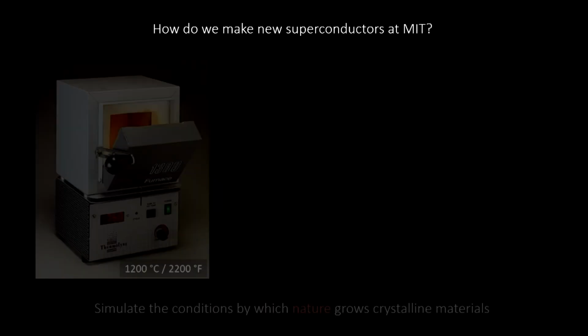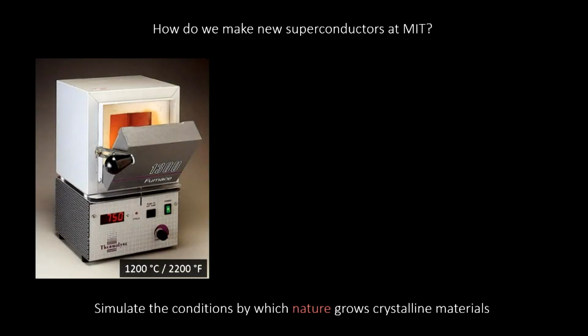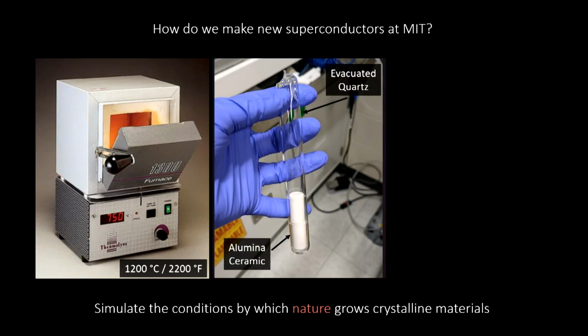In the Czochralski lab, we're doing very similar things. We're emulating nature and using these high-temperature furnaces that get up to something like 1,200 or 1,500 degrees Celsius. If you were to put all your chemicals into these high-temperature furnaces, they would all just oxidize, because we live in a very oxygen-rich environment. So in order to protect our chemicals, we seal them up into these double-sealed quartz tubes. All my chemicals are sitting in here, and this is evacuated, so there's no air in this environment.